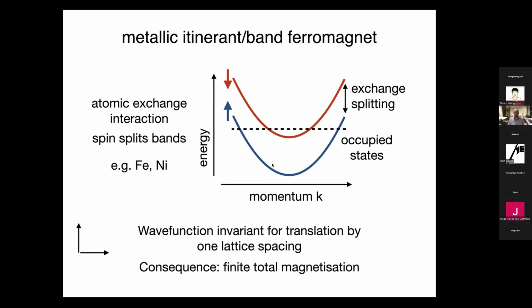So I have majority spin states that are occupied until the Fermi level, and minority spin states that are partially occupied or less occupied. And the splitting of the bands is given by the exchange splitting, which is related to the atomic exchange interaction, which is a large number in general. At least if you look at iron or nickel, this can be of the order of electron volts. And in the band structure, I have the same considerations of the wave function symmetry.